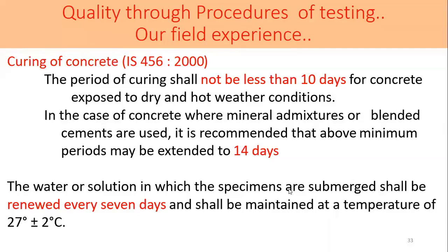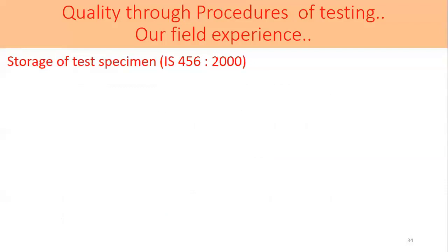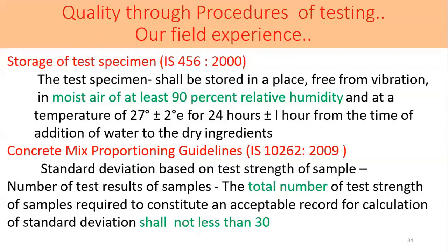And there are so many requirements, next please, requirements of storage and testing of the specimen. First of all, the frequency of sampling conditions: there is a code on how the sample should be taken, and those are required to be followed. After taking the samples, they are required to be kept in moist air, at least at 90% relative humidity. We should ask this question to ourselves: how many of us, for the sake of good quality testing, maintain 90% relative humidity? How many of us maintain the temperature of 27 degrees? This is important. Then again, the standard deviation aspects are ignored in the field. Concrete mix proportioning, there are guidelines as mentioned in IS 10262, and these are also ignored.